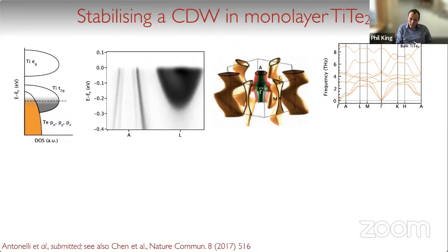instability in titanium ditelluride. Now we've already seen in the last talk some very nice measurements of the bulk three-dimensional dispersions of titanium diselenide, so again it's a system with rather strong out-of-plane dispersions. In this case, we've got a nominally d0 system. If you just looked at the formal valence of the titanium and the tellurium, you'd expect a d0 system with a completely unoccupied titanium conduction band. In actual fact, these two overlap rather strongly. So you have the p states from the valence band crossing the Fermi level and the d states from the conduction band forming a rather deep pocket at the Fermi level. And these disperse as a function of the out-of-plane momentum.